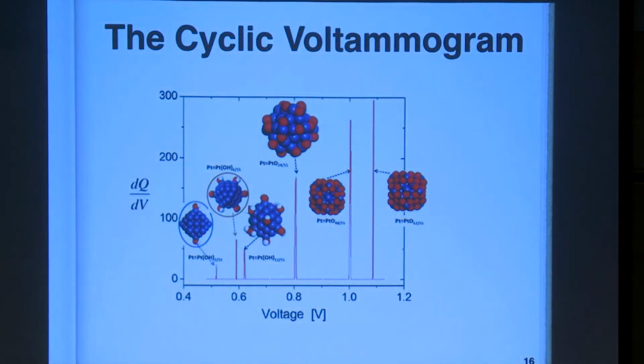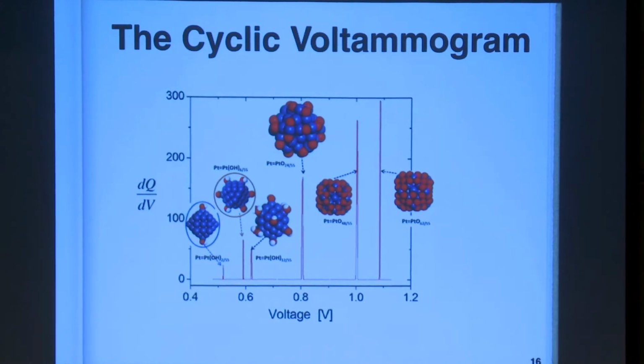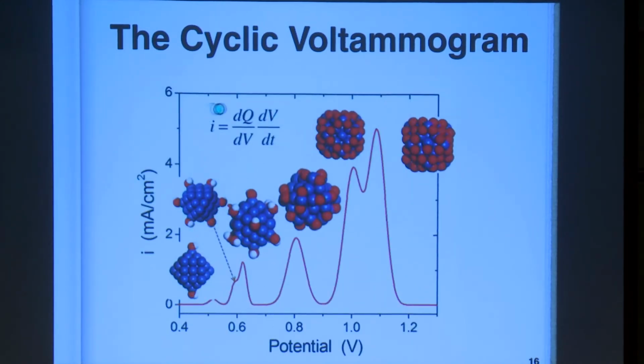How about electrochemical properties? Even first-principles calculations can predict cyclic voltammograms on the basis of a completely pure database of first-principles calculations. Here, you know exactly the structure, and we know how much proton and electron has to transfer to form these structures. If you apply this theory, the current density and the time variation of voltage, you can find the peak. Whenever there is an electrochemical reaction, you can see a peak like that. Then you can give this data to the experimental measurement, and you can validate the database.